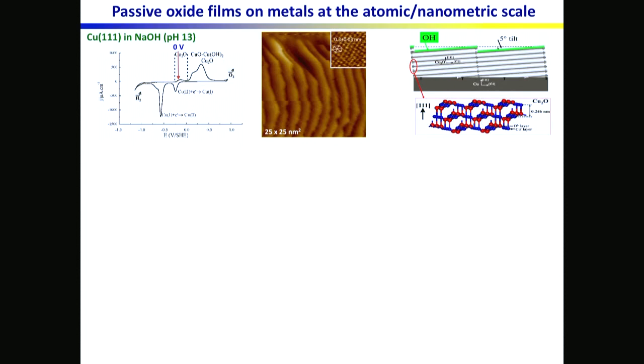The thickness here, you can see, deduced from the coulometric measurement, is just a few monolayers of oxide, so it's difficult to get X-ray diffraction patterns, except if you do grazing angle diffraction. But to do that, you have to go to a synchrotron, and actually there have been measurements also done on the synchrotron by another group who found the same structure as we had found already. So crystallinity of the passive film is a key feature for the stability of the film.